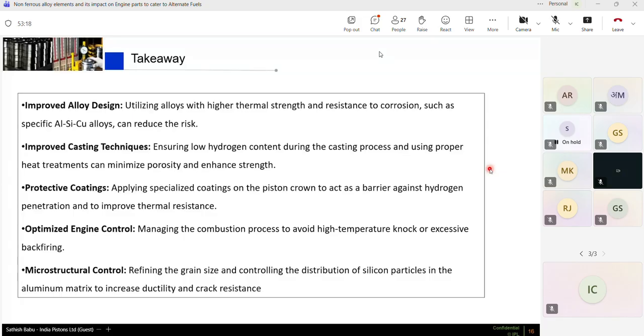Piston parts produced out of gravity die castings, we have challenges in creating a lot of defects and reducing the strength of the parts. Despite we allow this kind of defects in very traditional and conventional diesel and petrol engines, we do not expect this kind of defects to be prone to any kind of issues in the hydrogen engines, which is very severe in terms of piston breakage. So we are trying to reduce the porosity level in the castings and enhance the strength in the part. Beyond materials and other alloys, we also have coatings coming on the piston part, wherein some kind of aluminum alloys may require a new technology, which some customers may not pay for, and with different kinds of coatings on the piston crown portion, like a thermal barrier coating, will definitely act as a very good barrier against the hydrogen penetration.